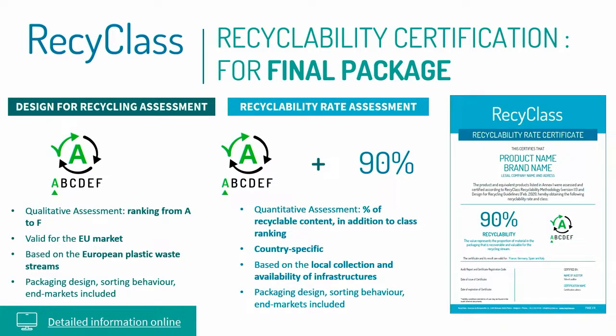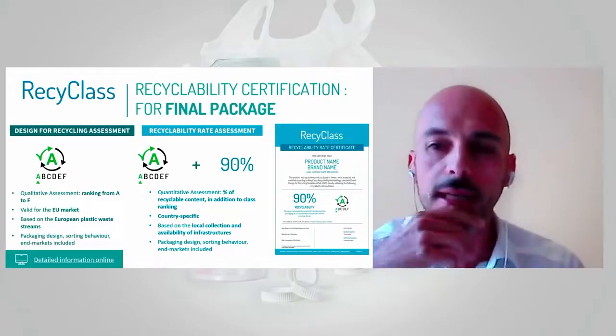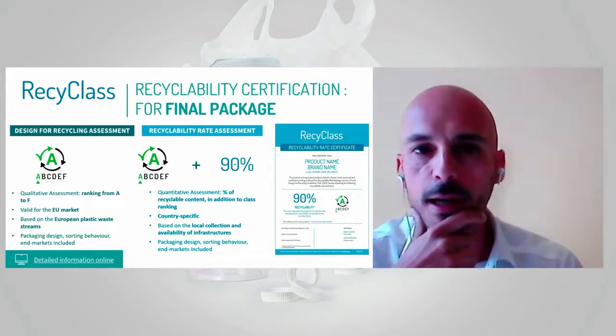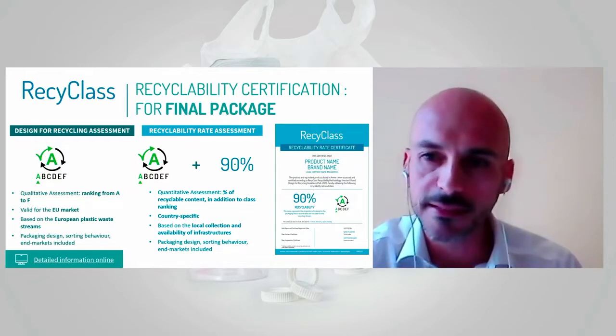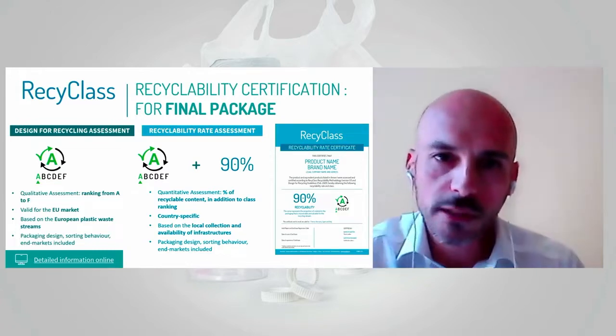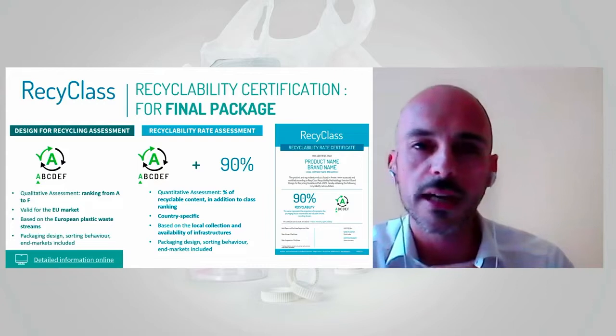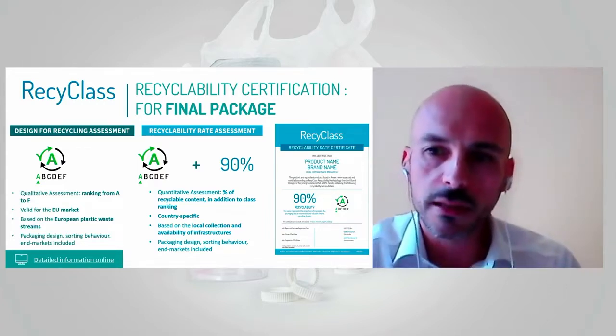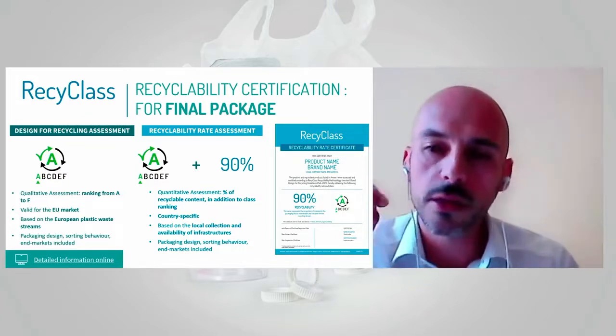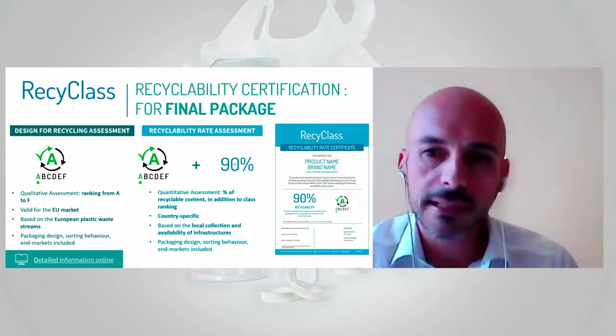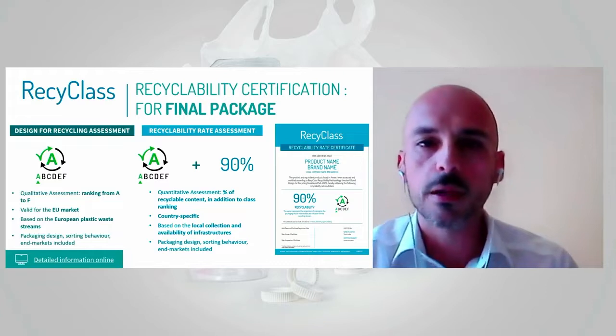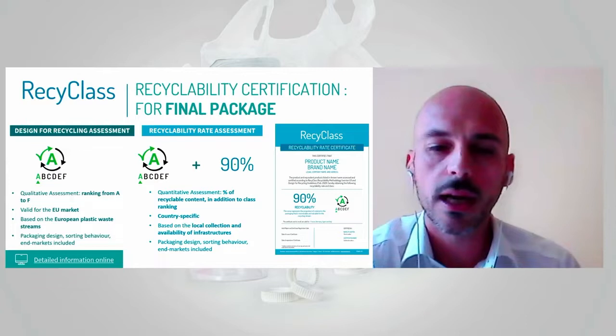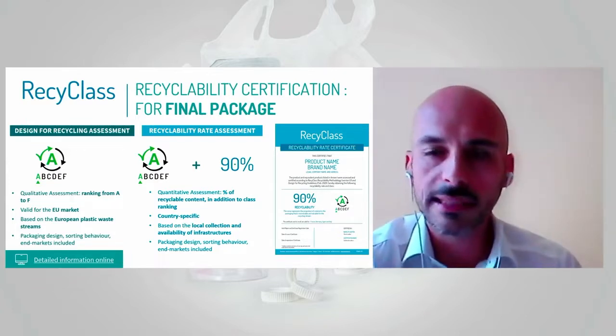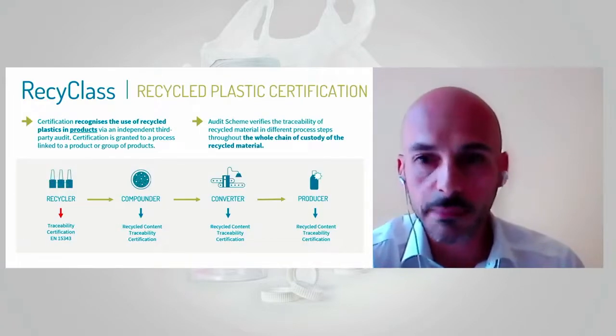But if there is at least one country in Europe, and this is the case for polypropylene flexible, where the packaging is collected, sorted and recycled, we can certify the packaging for recyclability with a pan-European approach. And we look to have also polypropylene flexibles certified by RecyClass with the recyclability rate assessment that is country-specific, targeting the audit in a specific geographical area. So where Sweden will start to recycle polypropylene flexibles in 2024, probably the recyclability rate will also be capable of capturing all the plastic packaging placed on the Swedish market that will get recycled, and will report, of course, also the recyclability rate, so the quantitative amount of valuable material that will get recycled with the packaging. The last is the recycled plastic certification.